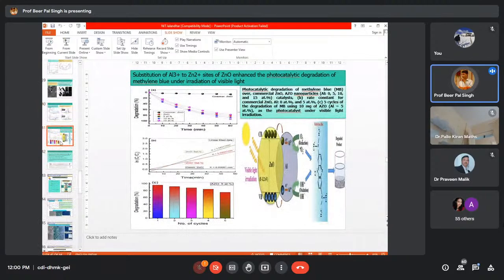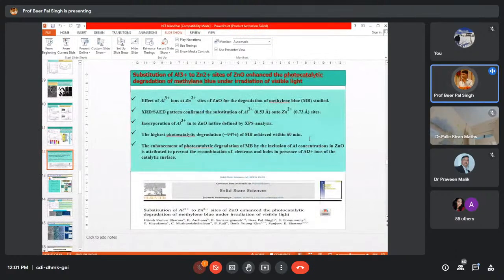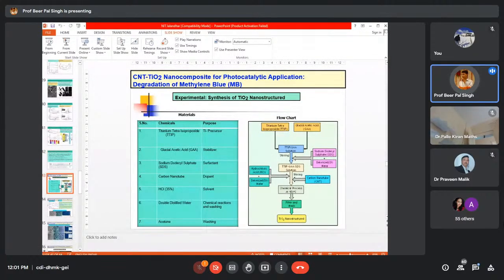This is all about the mechanism of how one can use aluminium doped zinc oxide for photocatalytic degradation of methylene blue. These are the results of that research, and we published it in Solid State Sciences. This is the CNT TiO2 nanocomposite, and again we used it for photocatalytic degradation